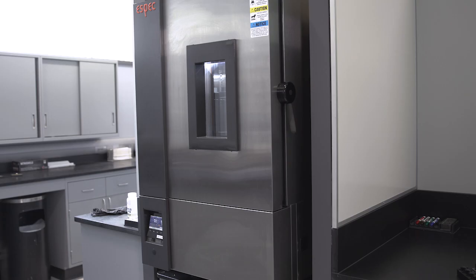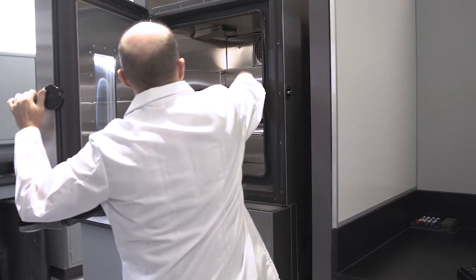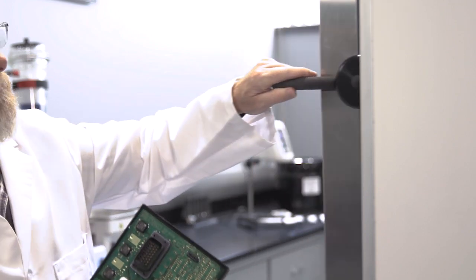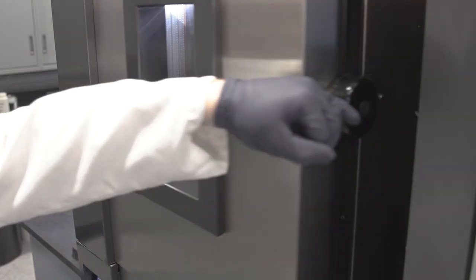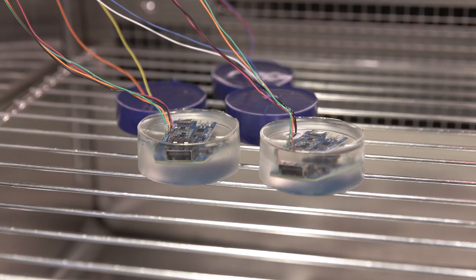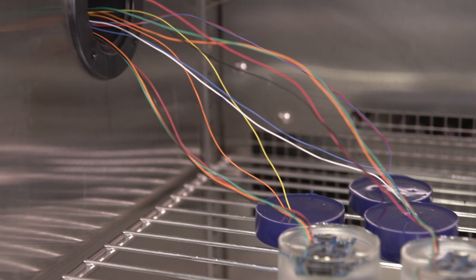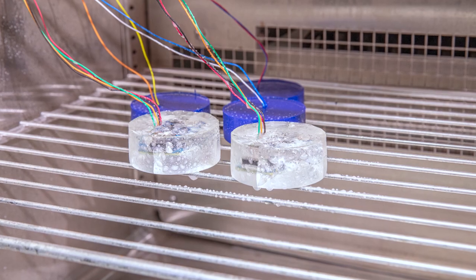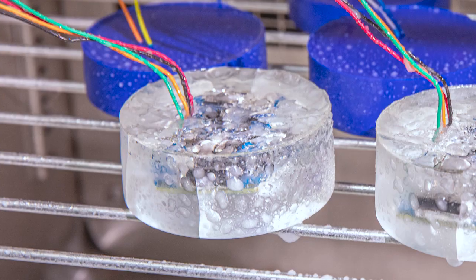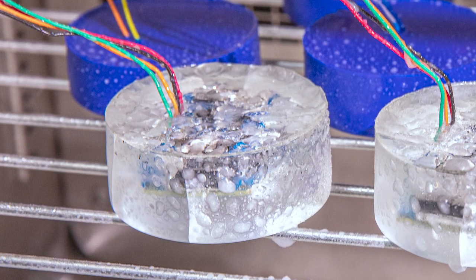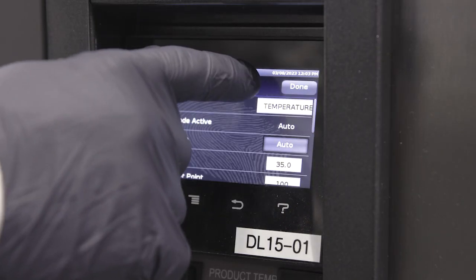Before potting compounds are integrated into power electronics, manufacturers subject these compounds to accelerated thermal cycling tests to simulate the conditions they'll face in real-world environments. This helps identify potential weaknesses and guides the refinement of the compound's formulation. We utilize our in-house thermal chamber to run life testing on actual customer parts. Our in-house thermal chamber allows us to test your potted electronics parts at your specified temperatures and humidities. The chamber has a temperature cycling range of -70 to 180 degrees C and a humidity cycling range of 15 to 95% relative humidity. These parameters are then used to set your desired testing protocol using the PLC control on the thermal chamber.